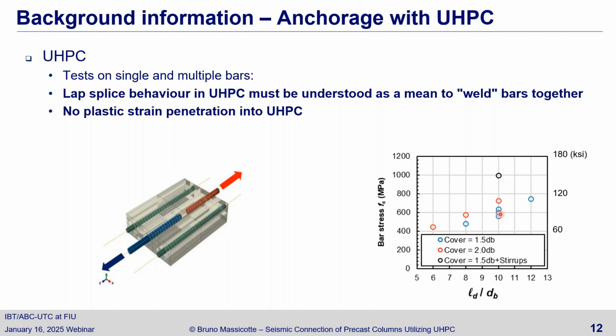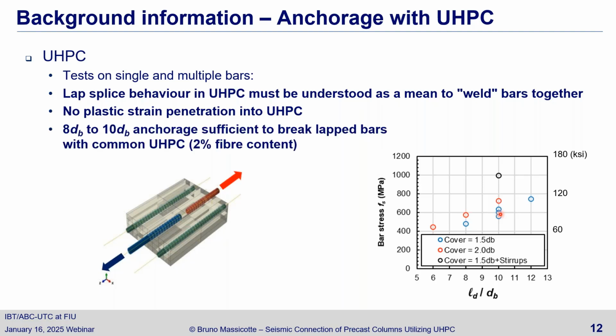And there's no plastic strain penetration into UHPC because the stress varies linearly and goes down quite quickly into the bar. So it's not like conventional concrete. And as mentioned before, if you have the 8 to 10 bar diameter anchorage, it's sufficient to break a normal reinforcing bar with a 2% fiber content of a commercially available UHPC.